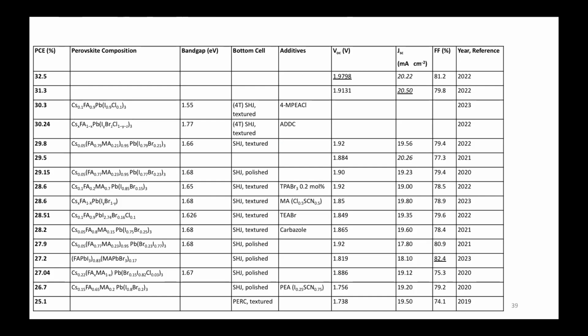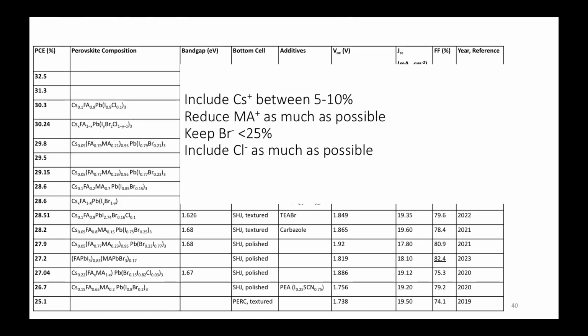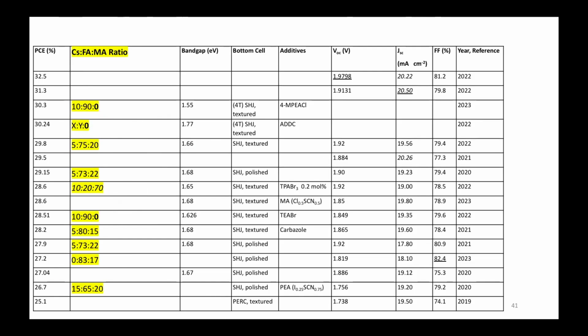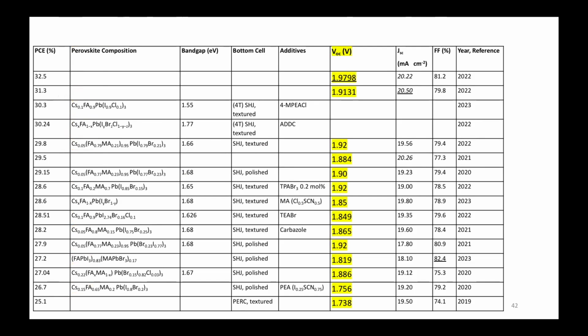If you look at the composition of some increasing efficiencies, there's a clear trend: you see that there's basically between 5 and 10% of cesium. There's not a lot of methylammonium, and there's not a lot of bromo. But more chloro, it does help. So they incorporate cesium as much as possible. This is the general trend. For composition, there you see the same. This is the cesium that's only there for 5 to 10%.